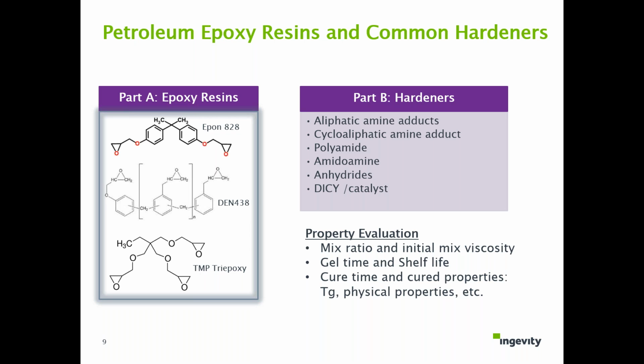And DEN 438, the second one, is a novolac epoxy with functionality somewhere around 3.6. I used this material a lot in the past to increase heat resistance and physical properties. It's a resin from Dow Chemical, right now called Olin. And the bottom one is a multifunctional epoxy diluent, TMP tri-epoxy. They also have a mono epoxy diluent called Epoxide 8 or Glydexx N10, a difunctional epoxy diluent, MPG epoxy, and they have a number of different products.